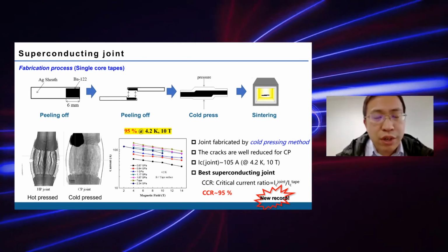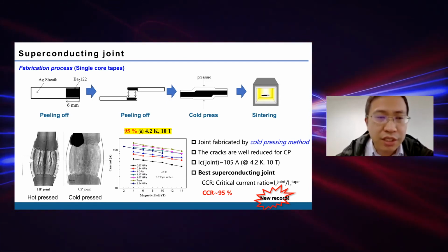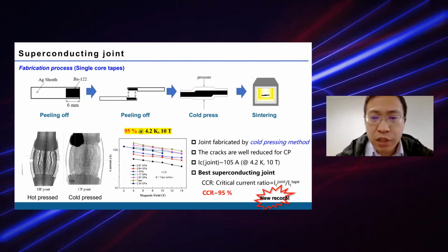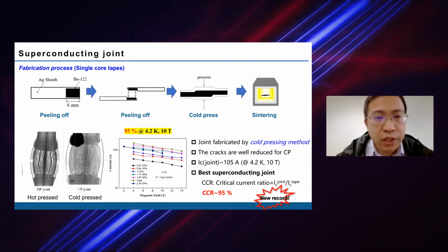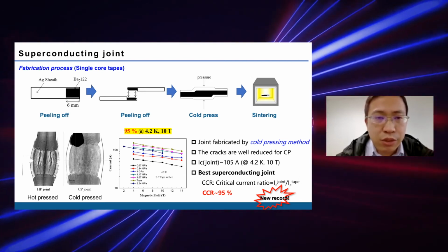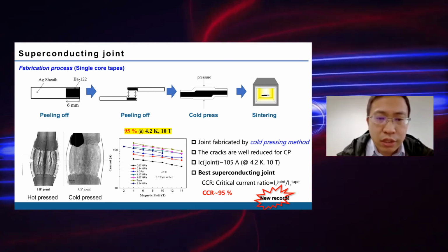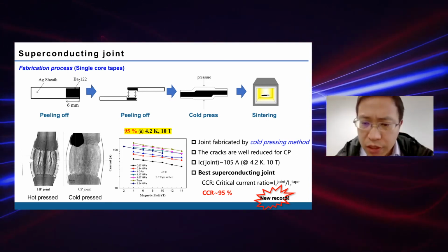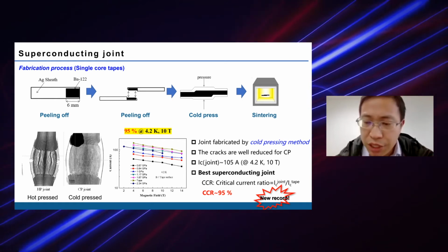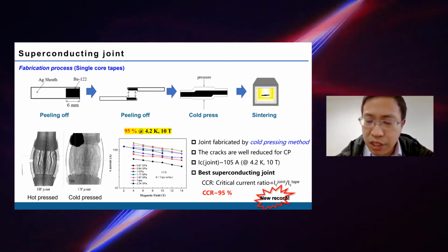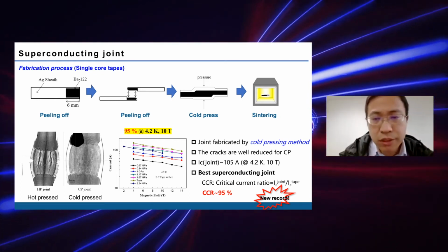Superconducting joints are very important for applications, and here we use a cold pressing method to fabricate a very good superconducting joint. The critical current ratio is increased to 95%. This is a new record.